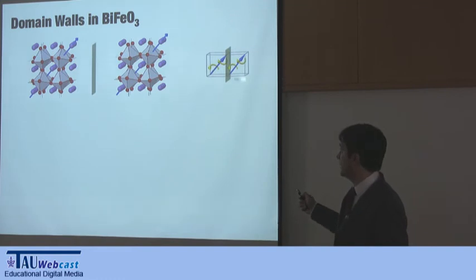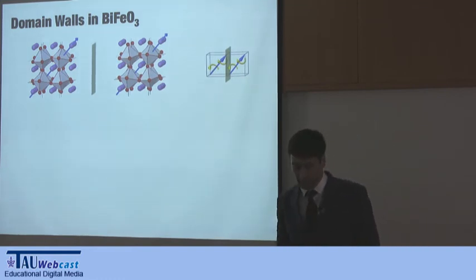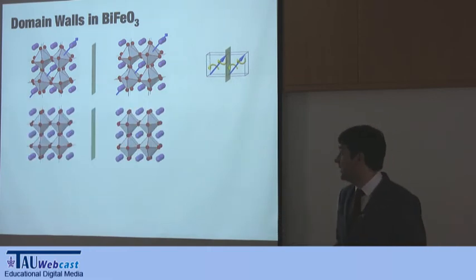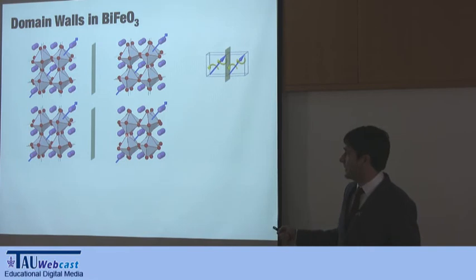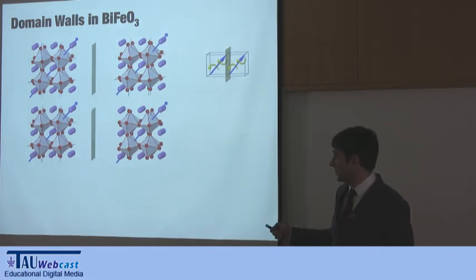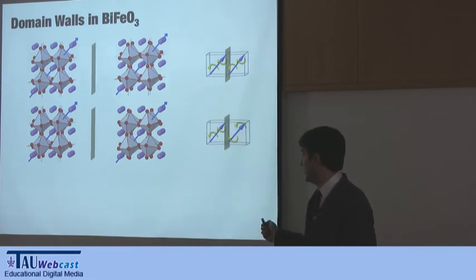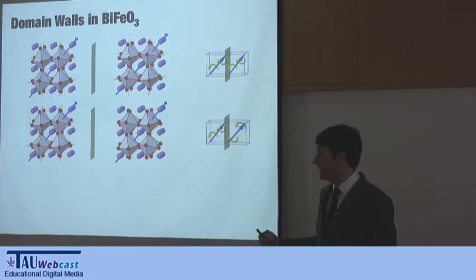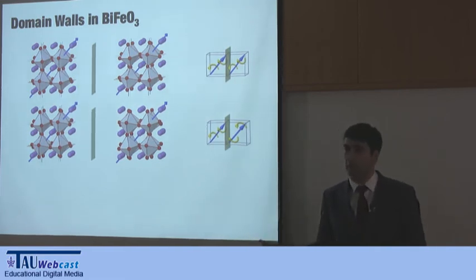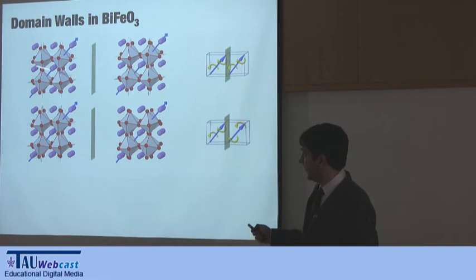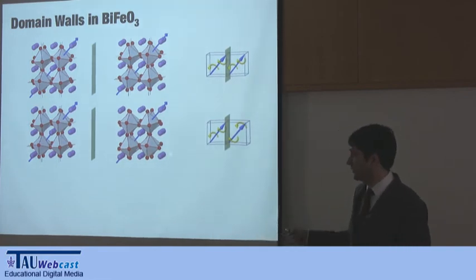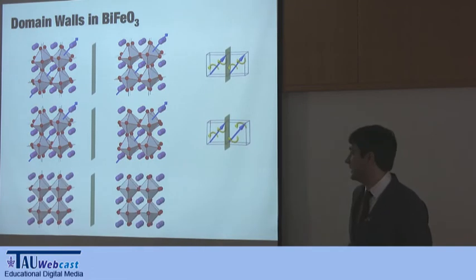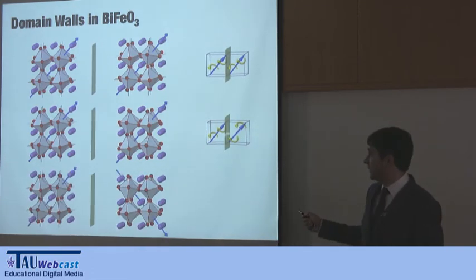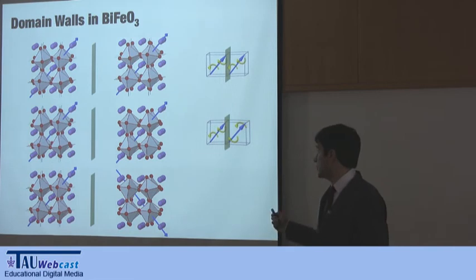I represent this with arrows for the polarization and with curved arrows for the octahedral rotation. You can have something very similar, which is polarization pointing in the same direction, but the octahedra go in the opposite way. And this I represent like this. And here you don't really have a ferroelectric domain wall, but you have a ferrodistortive domain wall, if you want. The octahedra don't match, so there will be some strain there. And finally, the same way you pick your polarization to go in the 1-1-1 direction, you can pick any of the equivalent ones that goes to any of the other vertices of the cube.